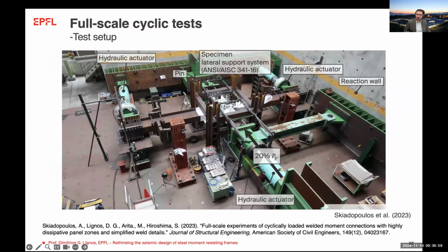So we did the beam-to-column testing of interior joints here, but in a horizontal fashion, where you see the two beams that were loaded with 2 actuators that you see at the beam ends. And the column here, that was a column with relatively thick flanges, like 70 millimeters, was subjected also to axial load. That was 20% of the nominal axial resistance of the column.